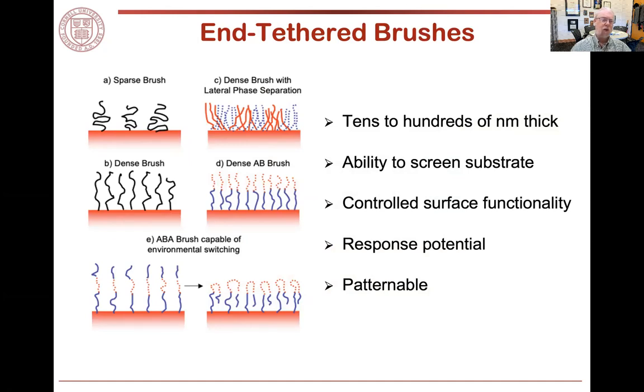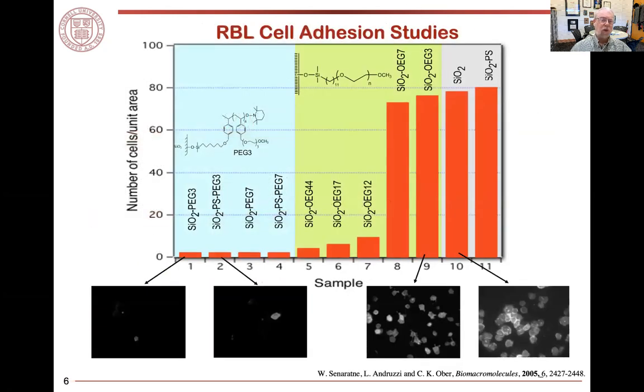The brush surfaces tend to be dynamic, and you can design them with a wide variety of chemical and structural architectures. And in work that we carried out some years ago, we were able to show that polymer brushes were extremely effective in preventing the attachment of cells to surfaces. At the time, we did a comparison with self-assembled monolayers and found that in our hands, the brushes were frankly outstanding. And you didn't really need to use very complicated architectures in order to be successful.